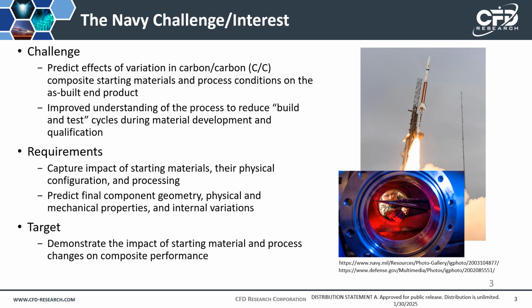We want to predict the sensitivity of the geometry of the final component, distortions that arise during these heating and cooling cycles, physical and mechanical properties, and internal variations such as the remaining porosity or defects including broken or distorted fibers that could weaken the composite. Our target is to demonstrate the impact of the starting materials and any changes or variability in the process conditions on the composite performance to help accelerate the transition from designs and small-scale tests, as seen in the inset figure on the right, to actual flight tests with repeatable composite properties.